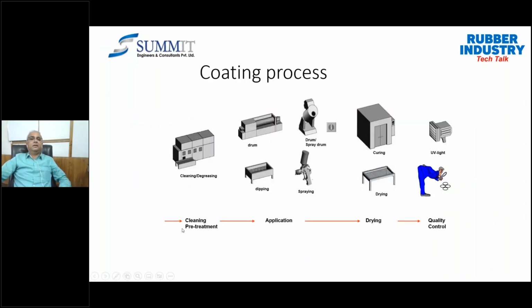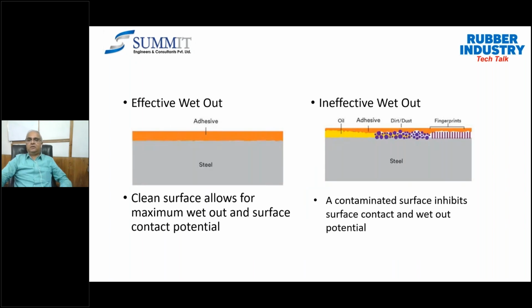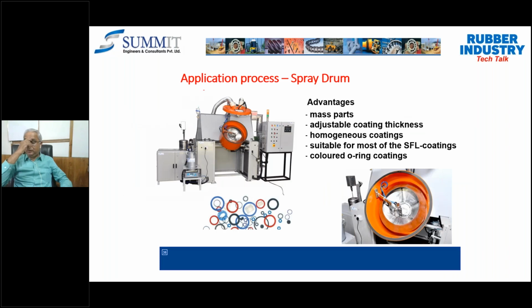We haven't talked about the cleaning or the pre-treatment. Now the application, depending upon the volume, the type of geometry, and the type of material also, right? We have got a variety of applications. People do ask me whether I can apply with the help of a brush. Yes, you can apply with the brush, but that will not give uniformity on the surface, because normally the dry film lubricants have limitations in terms of process parameters. That is, you require a coating thickness ranging from 4 microns to 20 microns. If somebody comes and tells me, okay boss, I'm using a rubber component, I want 25 microns of coating thickness, then I would say better not to do a coating of 25 microns. This process will be a special or separate process.